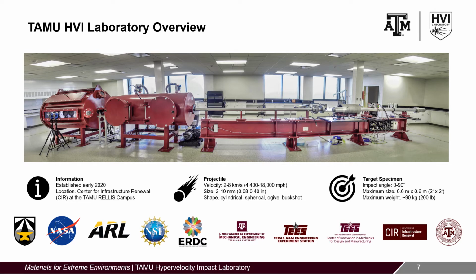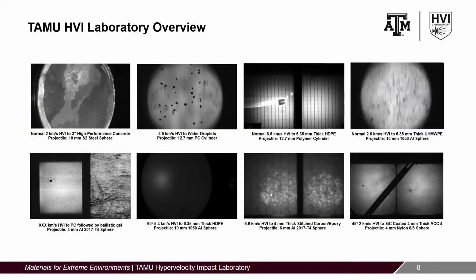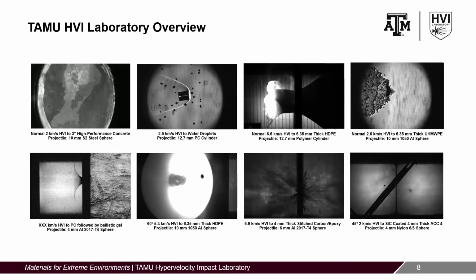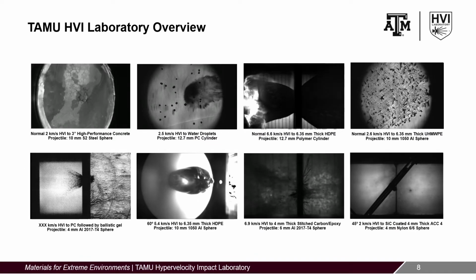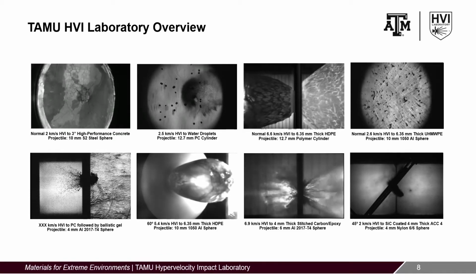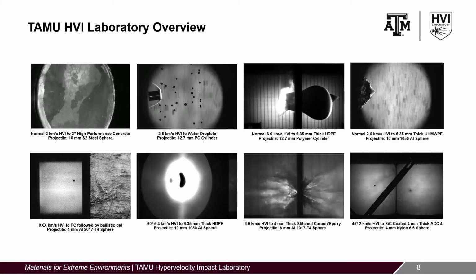The experiments in this work were conducted using a two-stage light gas gun shown on this slide, which is located at the Hypervelocity Impact Laboratory at Texas A&M University. The two-stage light gas gun was built by Physics Applications Incorporated and is capable of accelerating 2 to 10 mm diameter projectiles to velocities of 2 to 8 km per second. The lab is part of the Materials for Extreme Environments research group that encompasses other experimental expertise and novel modeling efforts. Apart from the work discussed in this presentation, our group also studies impacts to various concretes, polymers, composites, and water droplets at various impact configurations, as well as shock fronts.